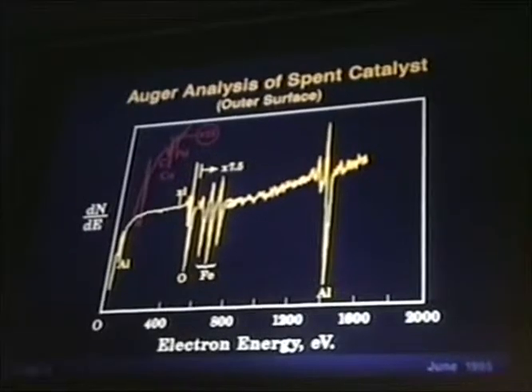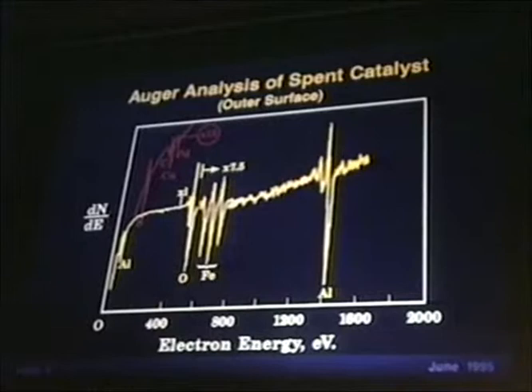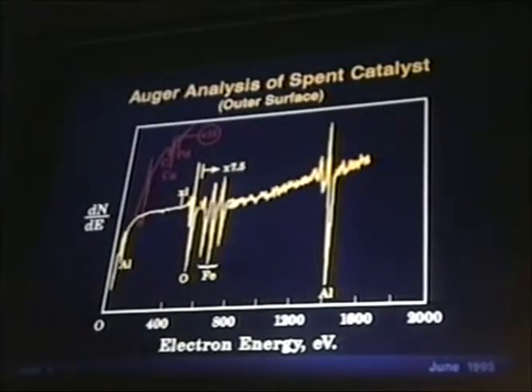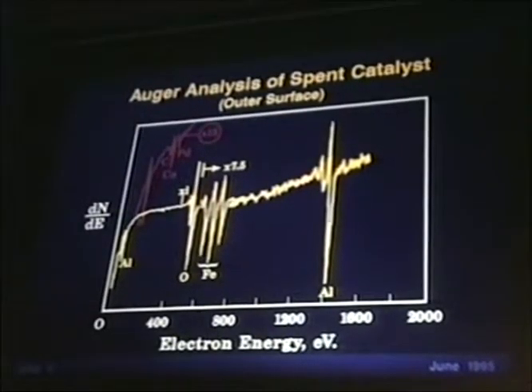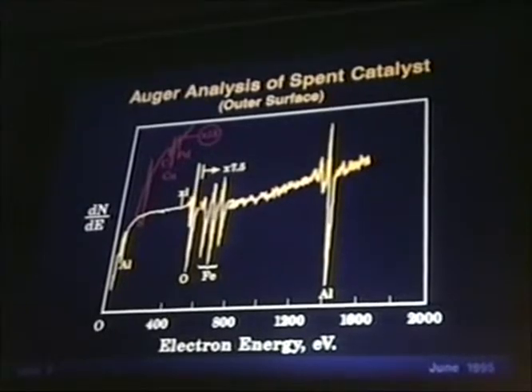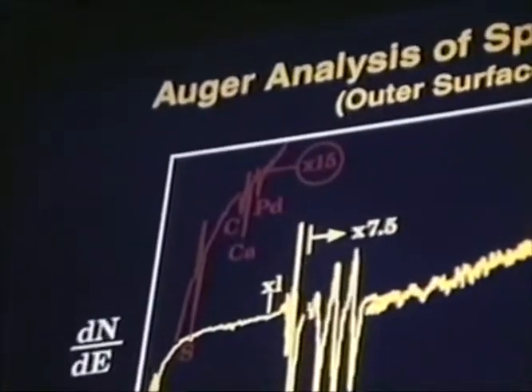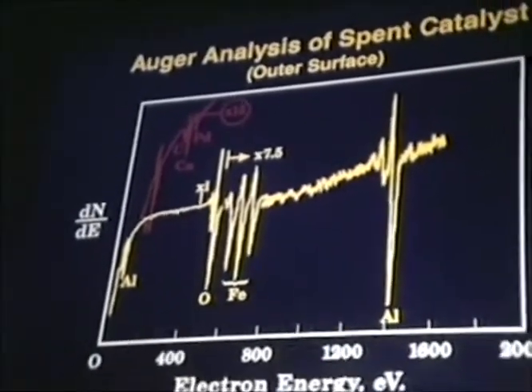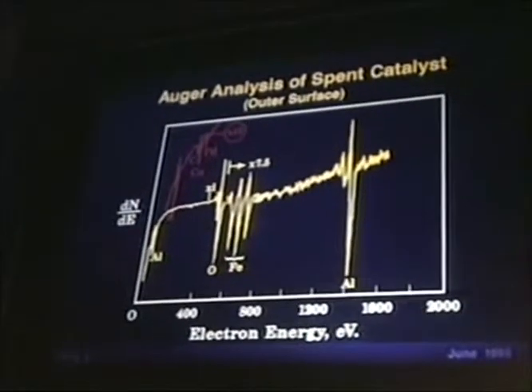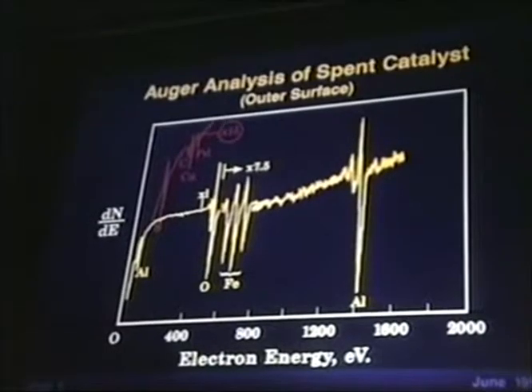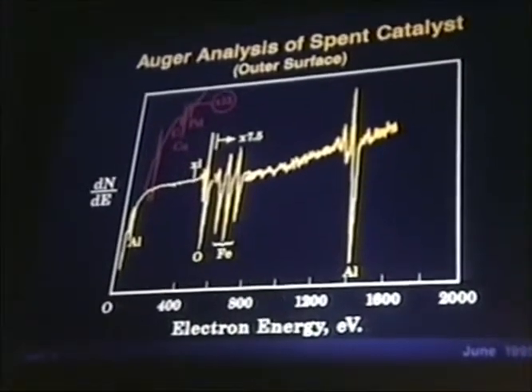Auger analysis of the spent catalyst, and by the way, I'm only showing the outer surface, showed that palladium on the normal scan, which is in orange, is not even visible. But certainly at a fairly normal scale, iron is dominating the surface analysis. In addition, you see the co-promoters have also disappeared and are not visible.